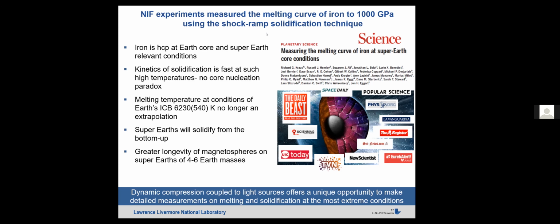Yeah, thank you, Burkhard. That is an important aspect, and one that we've labored over a tremendous amount. Amy Yannay and John Eggert have spent a tremendous amount of time looking at this. And actually, for the specific question of how sure you can be, for the background subtraction algorithms, there are a couple of different ways to do it, and we looked at a couple of different ways. The background subtraction algorithms are most likely to take away the liquid structure. So we can be fairly certain, and we looked at the signal to noise, fairly certain at the 5 to 10% level that there is no solid fraction.